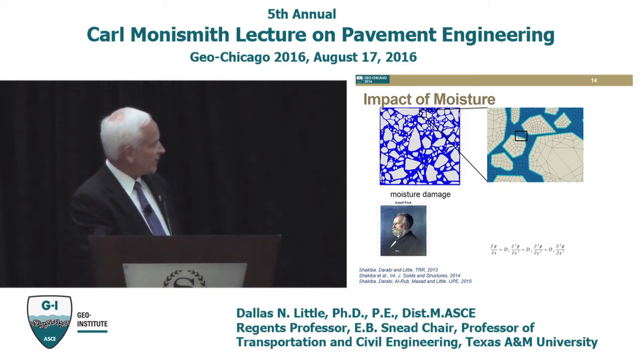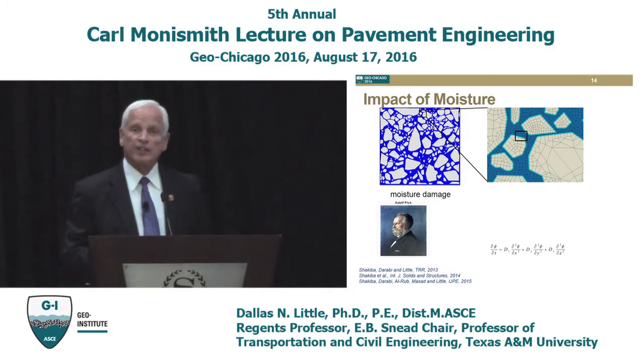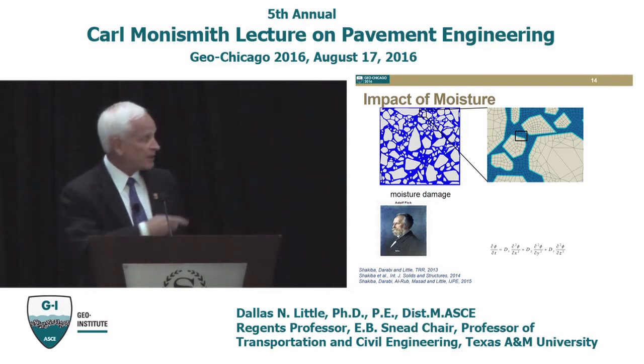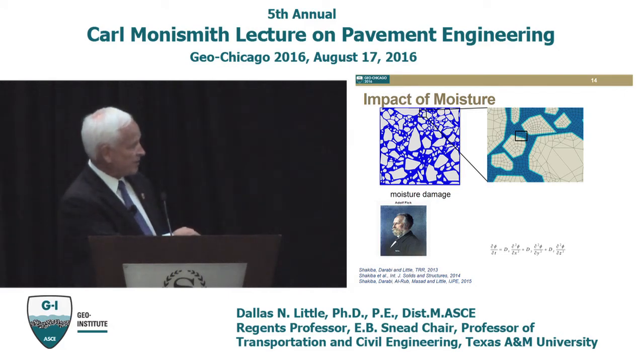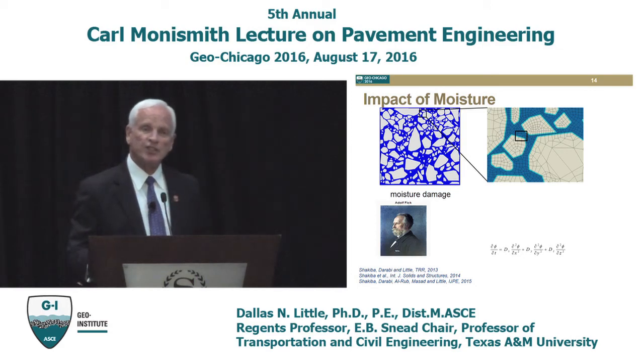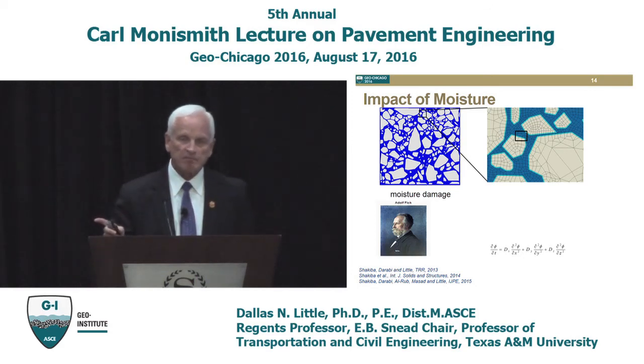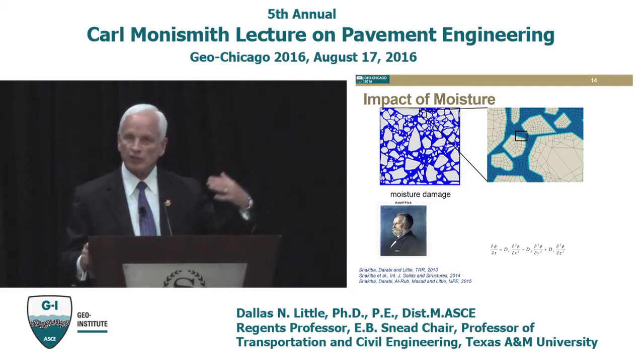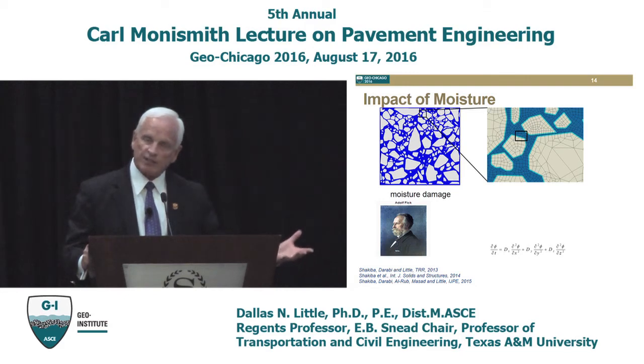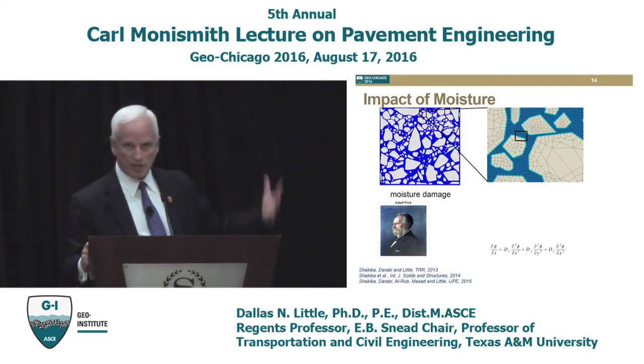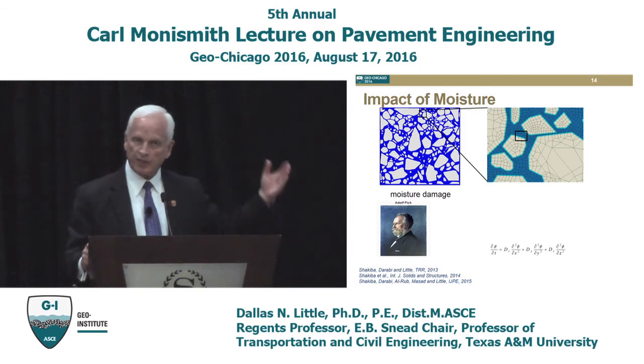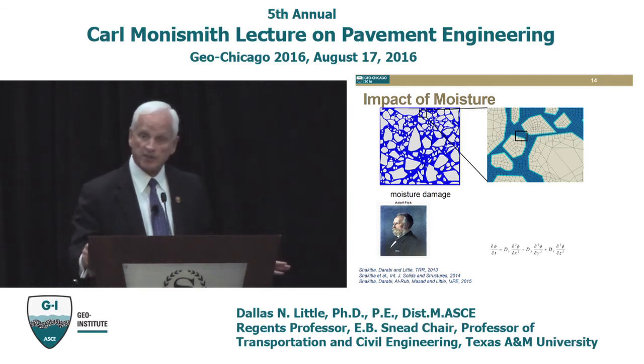When we look at diffusion, and by the way, if you look at Fick's law, it's a second order differential equation, but the material science is in the D terms. The material science is in the D terms because that is diffusivity. And what we did very carefully in the ARC project was we measured diffusivity. Diffusivity of the aggregate, diffusivity of the mastic, and diffusivity of the mixture. You've got to have that to be able to understand how moisture diffuses into asphalt.